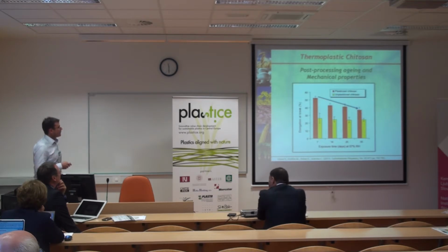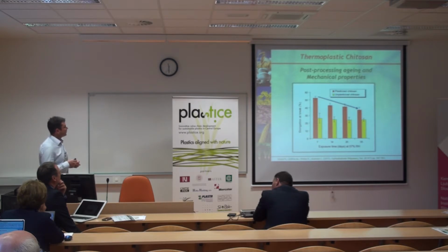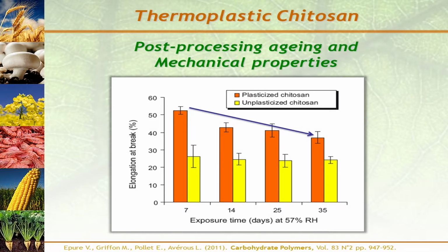So first we were interested in the post-processing aging of such chitosan-based material. And here is the evolution of the mechanical properties, the elongation at break with the exposure time or storage time in days at a 57% relative humidity condition. And here you can see that the properties of the materials evolve due to changes in the water content and in the crystallinity of the material.